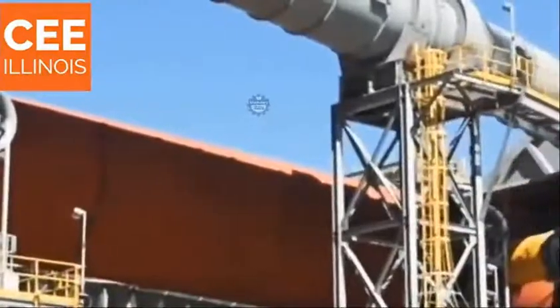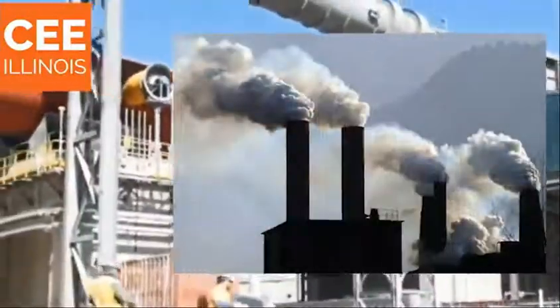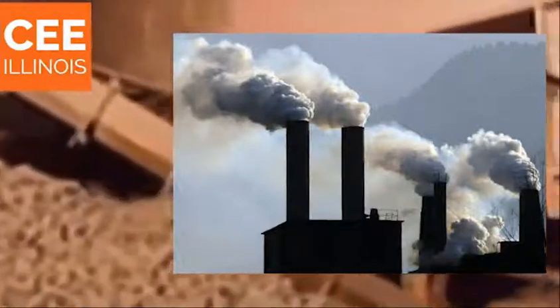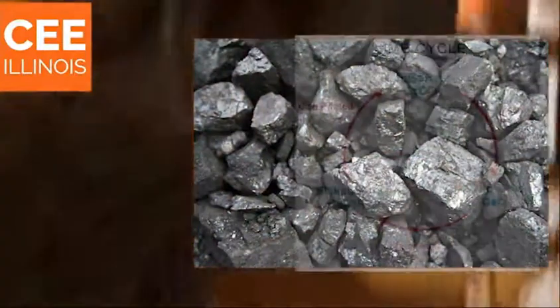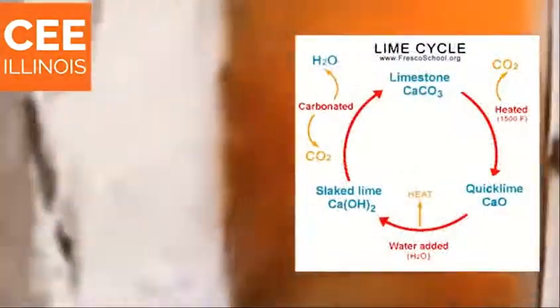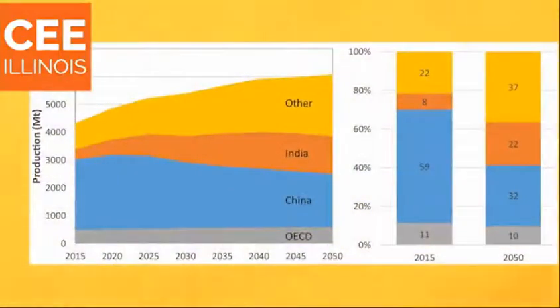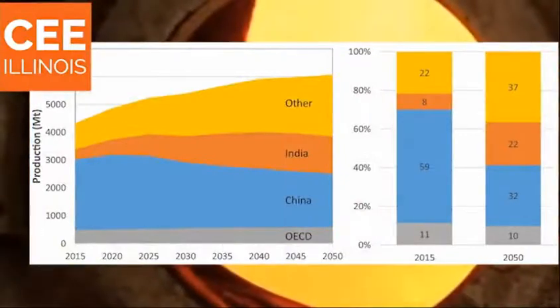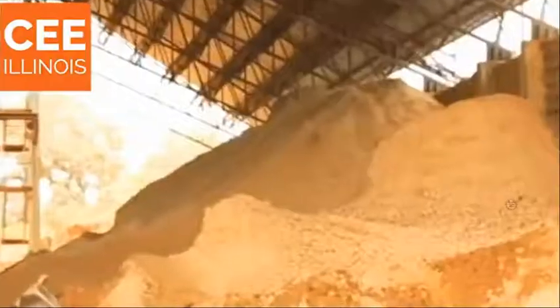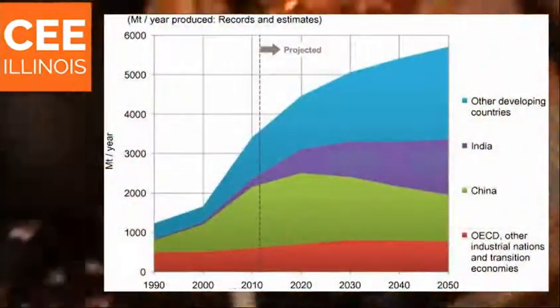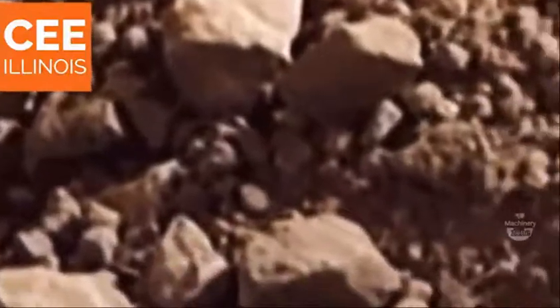The resulting intermediate material, clinker, generates on average 842 kilograms of CO2 per ton. As much as 40% of the total CO2 emissions come from fossil fuel combustion, while the remainder comes from limestone decomposition during the calcination process. For citizens in developing or low-income countries, cement production needs to increase to meet their demands for decent built environments. CO2 emissions from cement production are expected to increase by 260% between 1990 and 2050. The 450 ppm IPCC mitigation scenario would call for a 50% reduction in anthropogenic CO2 emissions by 2050. By this year, the cement industry will account for about a third of all CO2 emissions if new methods are not implemented to reduce emissions.